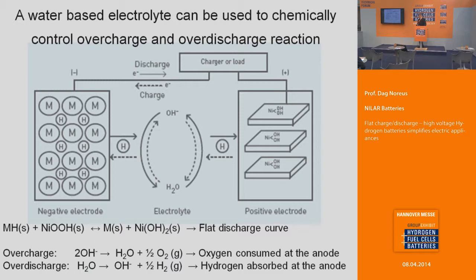And in the water-based electrolyte you can chemically control overcharge and over-discharge reactions. So you have a little bit less capacity here. And when you overcharge the battery, this will pick up hydrogen and it will go into the metal hydride. And if you do not have enough capacity here, it will take hydrogen from the electrolyte, releasing oxygen. And this oxygen can then be consumed on the metal hydride, on the anode. And when you over-discharge, you're trying to push hydrogen back here, but there's not enough space. So you will have an evolution of hydrogen. But then you have an empty metal hydride in the anode, so that will take care of that. So with a hydrogen battery you can build the overcharge and over-discharge reactions into the battery.